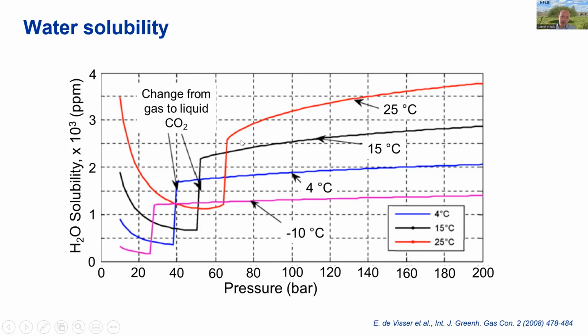What happens when the pressure drops? And this can happen maybe due to an upset in conditions in the pipeline or at a particular component of the pipeline where there is a pressure drop. The solubility can dramatically drop at any of these temperatures. And particularly at lower temperatures, the solubility in the gas phase drops down to quite low values.